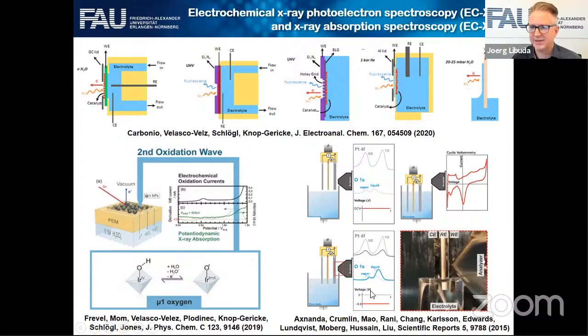So this is the original publication illustrating how it works, from the Advanced Light Source, Berkeley. What you do is you dip your sample into the electrolyte, pull it out, and then hope that there's a small film of electrolyte on the surface in which you can control the potential. This is a beautiful experiment because it allows you to do the spectroscopy on any surface. Many groups are implementing or have been implementing that in the meantime.